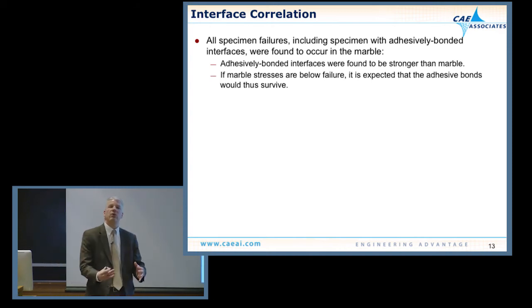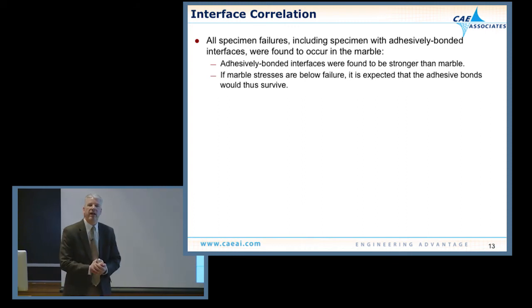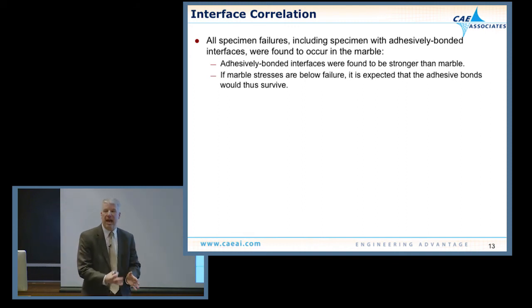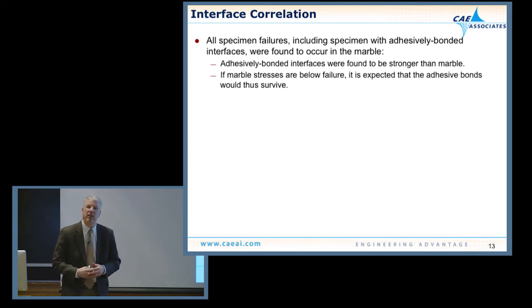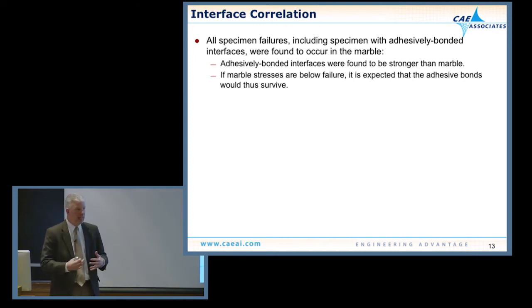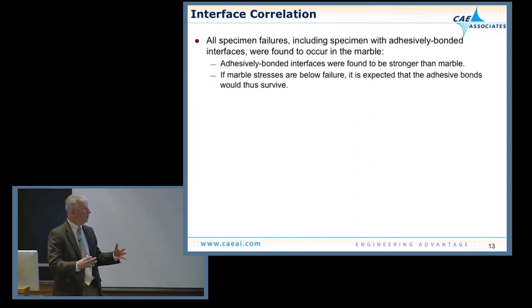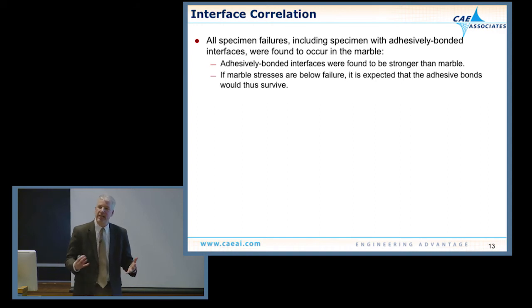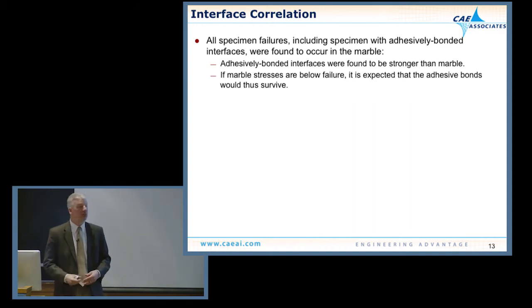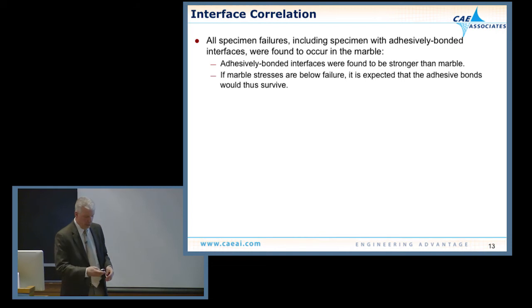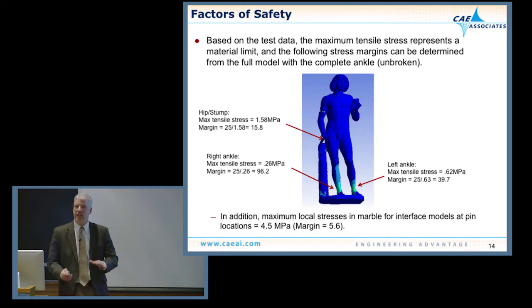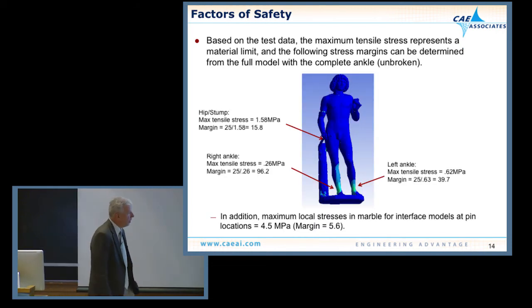Everything was great until, as we started looking into everything, we found out that almost all, literally all but maybe one, of the failures were not delaminating. Everything from their specimen testing was failing in the marble. In other words, the adhesives were as strong as the surrounding marble material. So what that means at this point is we don't really have to worry too much about the delamination. My job is finished, and I handed it off to Pat to say, okay, you really just have to concentrate now on the marble.